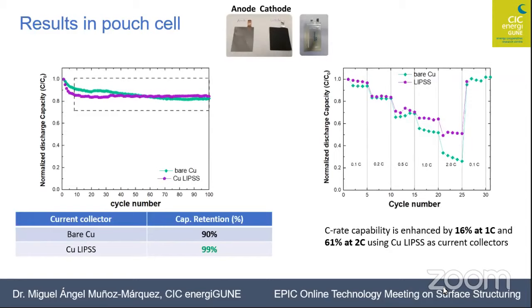With this structuring, as I was saying, we managed first to improve the stability of the battery. If you see on the left-hand side, you will see a green line, which is the capacity of the battery as you cycle, in a total of 100 cycles. The green one corresponds to a bare copper current collector, and the purple one corresponds to a structured copper current collector. So you can see, although you have a small drop in the capacity, then the capacity remains constant with the cycles, whereas in the bare copper it drops. So we prove here that this structuring is very interesting for the stability.